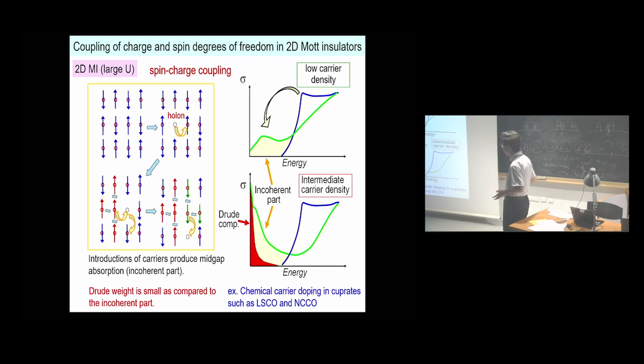Further carrier doping gives rise to the metallic state. However, the Drude weight is small as compared to the incoherent part. The electron doping is in the same situation. These features were indeed observed in the chemical carrier doping in cuprates.